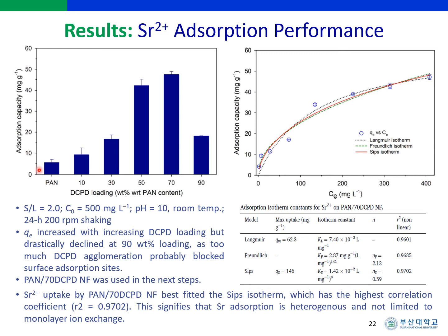However, uptake capacity declined at a DCPD loading of greater than or equal to 90%, which could be attributed to too much DCPD aggregation and observed spattering of PAN-DCPD aggregates out of the mandrel collector during electrospinning, hence causing self and PAN blockage of the adsorption sites, and lower presence of DCPD particles on the nanofibers, respectively.